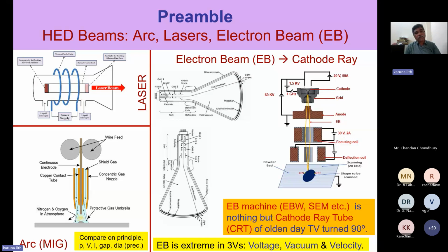So that's the kind of scanning speed we are talking about. That is because in the case of arc, the movement of the torch is by the mechanical movement of the table or something like that. So you use regular motors for it. In the case of laser, you have a galvanometer which has a very fine, few grams of mirror oscillating. Whereas here you use coils. Okay, you use a coil or some kind of electrostatic force to deflect the beam. So there's absolutely no inertia.